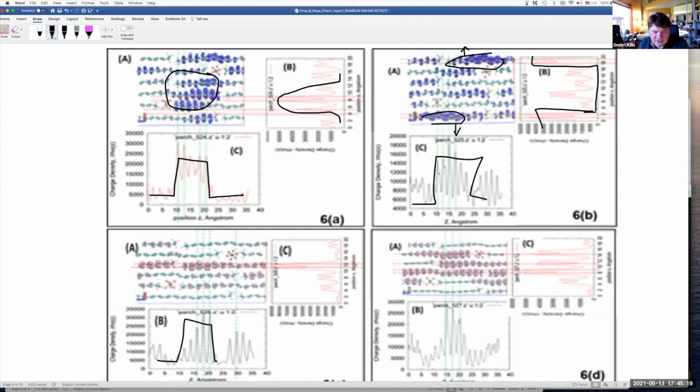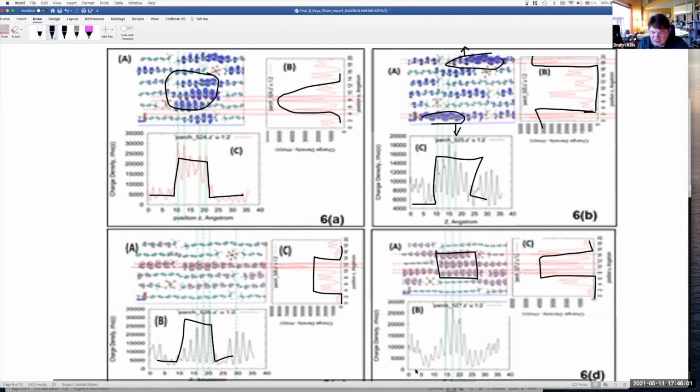Differently from the undoped model, the charge density prefers the space between the dopants. So the presence of the dopants themselves does not carry charge, but they affect charge distribution on the nearby strands. And this is very similar to the project that Dr. Khan is doing. He was not showing orbitals today, but in his project also this covalent doping doesn't have any charge on itself, but it affects charge distribution on the conjugated system nearby.